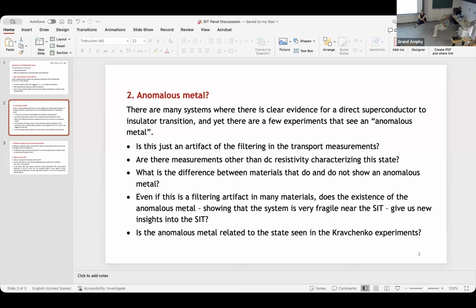So critical resistance, for the ideal situation, of course, people always say 6.45 kilo ohms, but it's for a very ideal situation. It's not like that in a real situation. Actually, whatever is lower than this value or much larger than this value, in some kinds of disorder we can still see such resistance saturation at a very small value, approaching zero temperature.